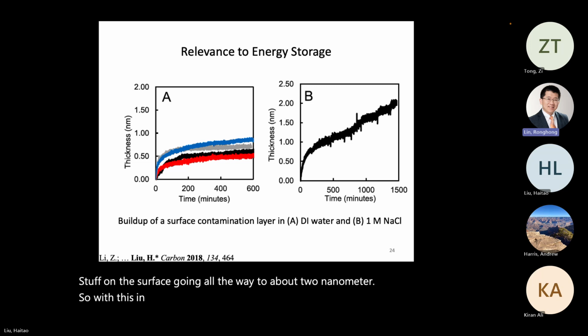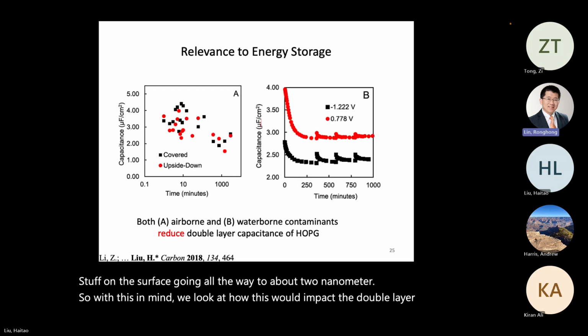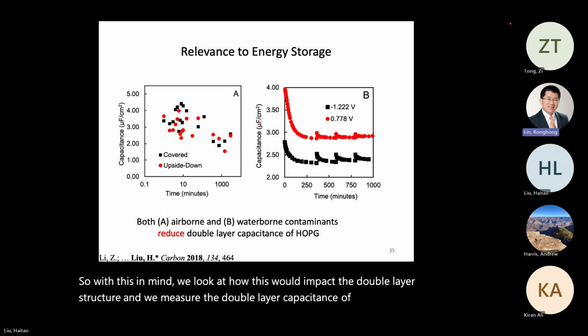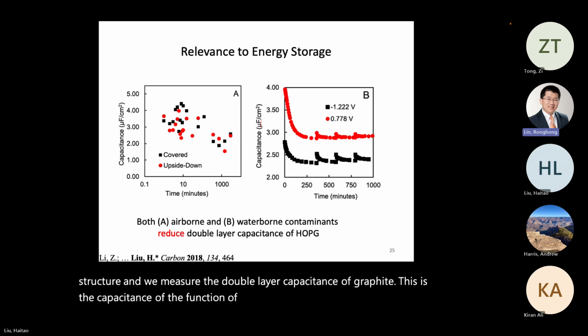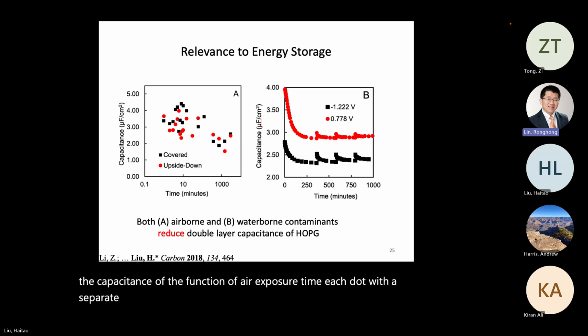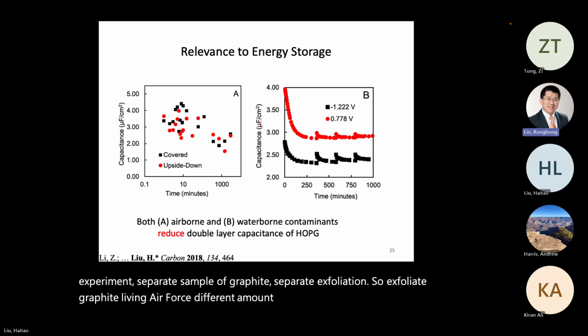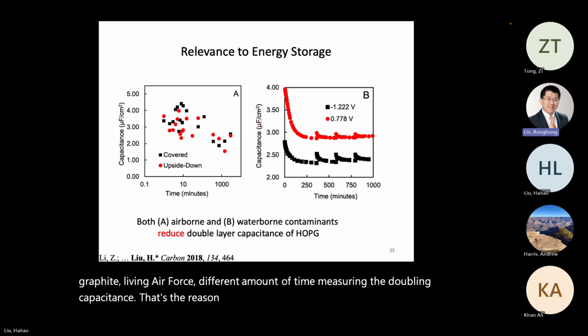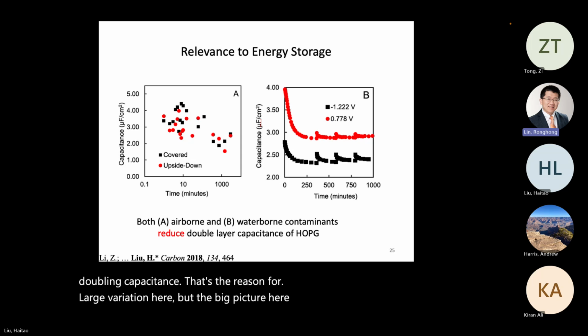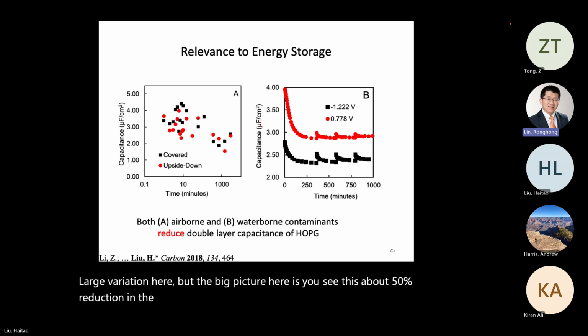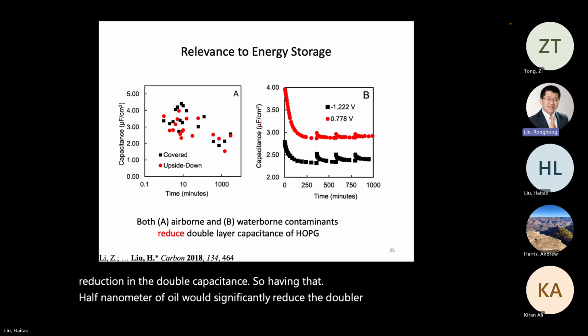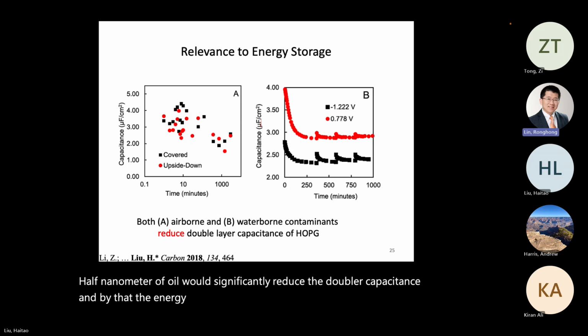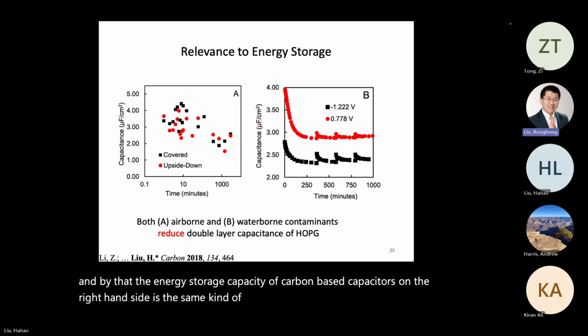So with this in mind, we look at how this would impact the double layer structure, and we measure the double layer capacitance of graphite. This is the capacitance as a function of air exposure time. Each dot is a separate experiment, a separate sample of graphite, separate exfoliation. So we exfoliate graphite, leave it in air for a different amount of time, and measure the double layer capacitance. That's the reason for the large variation here. But the big picture is you see about a 50% reduction in the double layer capacitance. So having that half nanometer of oil would significantly reduce the double layer capacitance, and by that, the energy storage capacity of carbon-based capacitors.